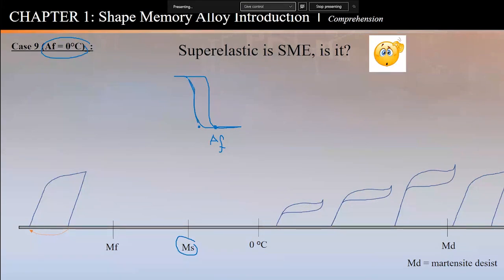What happens when you're fully martensitic? We're down here. When you load and you unload and then you heat, you recover. So this is what I told you, the shape memory effect. You load and unload and you can get the shape back by heat. A minute ago, I showed you this schematic here. If I take material and I load here versus here versus here and so on, I get a nice superelastic curve.